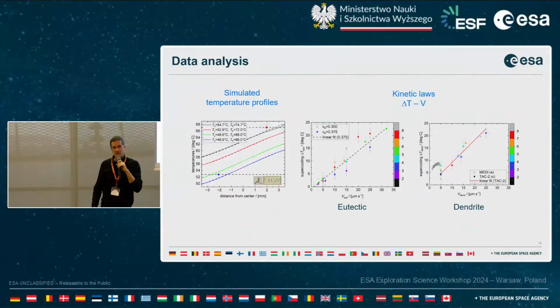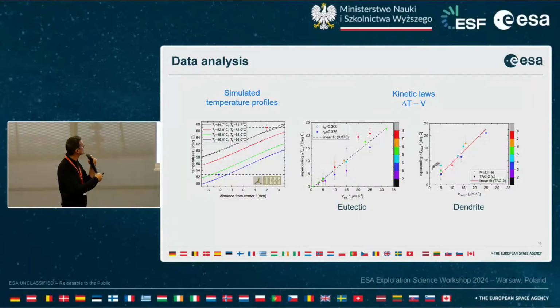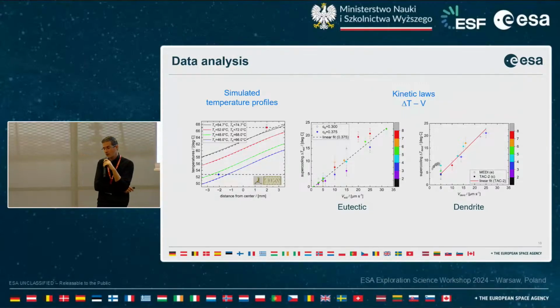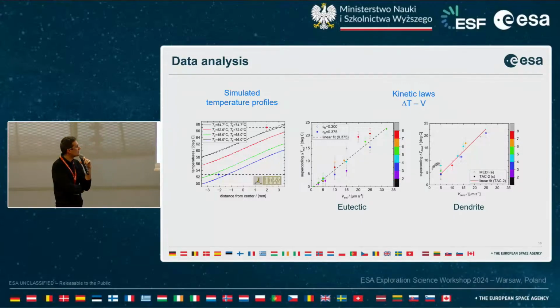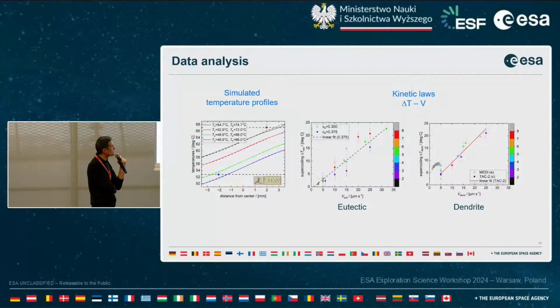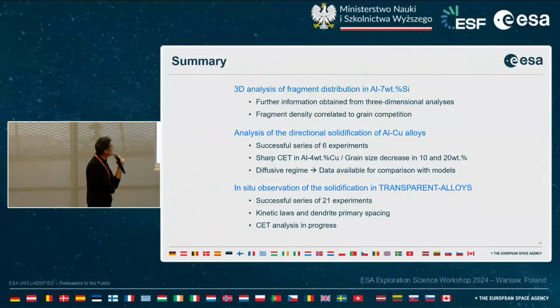So what is nice with this experiment also is that the temperature profiles have been simulated, which is quite important if we want to carry out further quantitative characterizations, such as determining kinetic laws, if we try to relate the growth velocity of the dendrites with the undercooling. So it was done both for the eutectic and the dendrites. And this is interesting especially for 111 dendrites, for which the kinetic laws are not well known, and it can be used to compare with further theoretical models in the future. So this is what I wanted to show you about the activities.